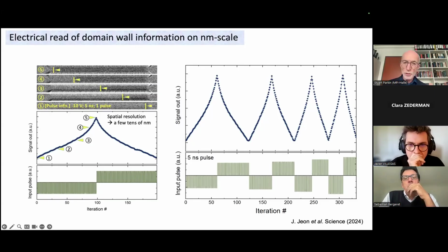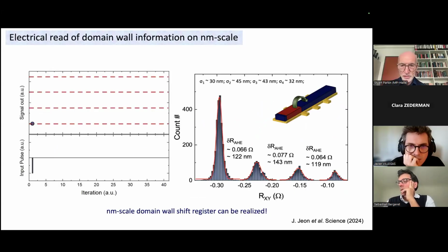And why this is so remarkable is that we've gone from micron-wide racetracks, where we could optically detect the domain walls, to these racetracks, which are just a few tens of nanometers wide, yet it turns out the domain walls move at roughly the same velocity for the same current intensity. And this was quite a surprise. We thought that the edges would be quite rough and that would deter the motion of the domain walls. It turns out that this isn't the case. So this is a very interesting point.